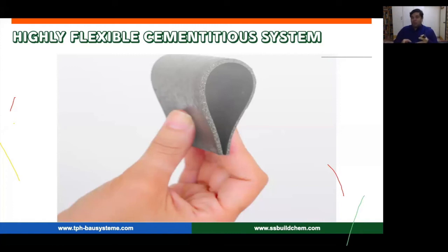No, that doesn't work. Because cement alone, once you mix it with water, has a tendency to shrink. So no matter the amount of polymer you add to it, after some time, the entire system tends to shrink, it tends to dry out very easily, and it tends to crack. And normally when that happens, that is when your waterproofing fails. So when we talk about highly flexible cementitious or 2K systems, component A is a powder component which has been very specially designed.